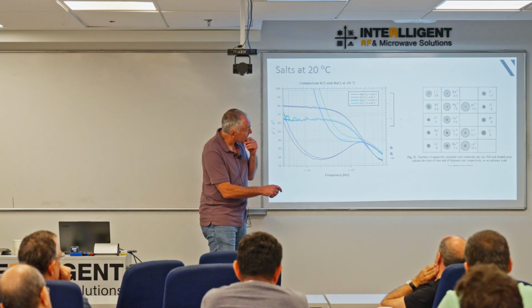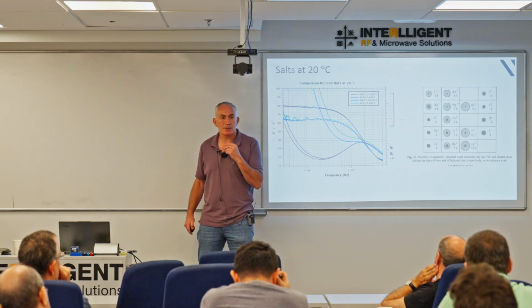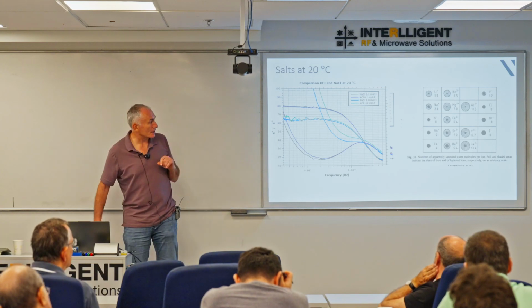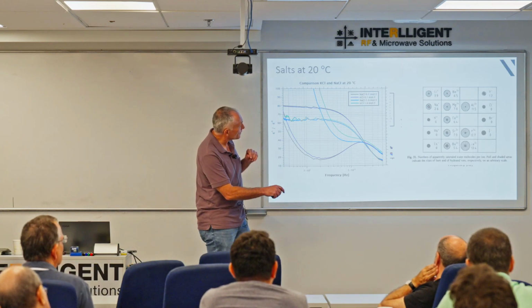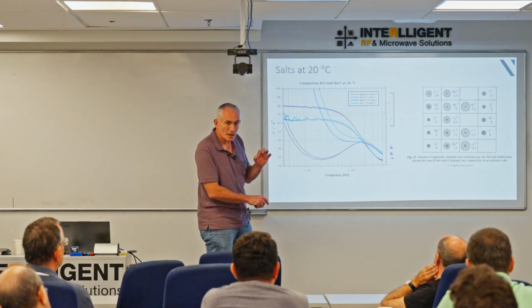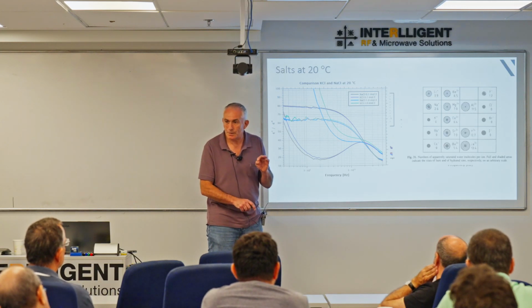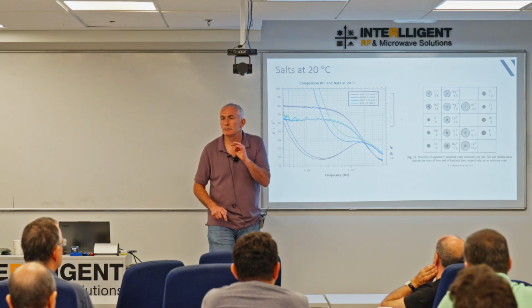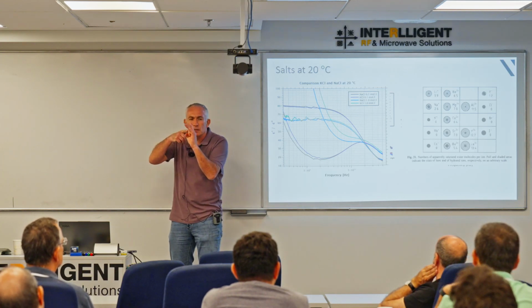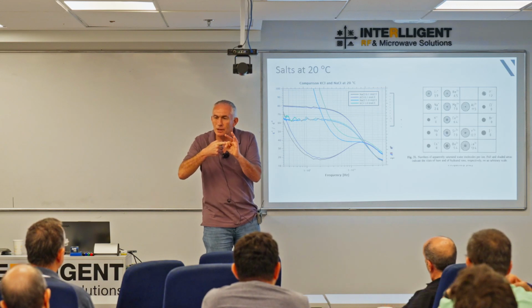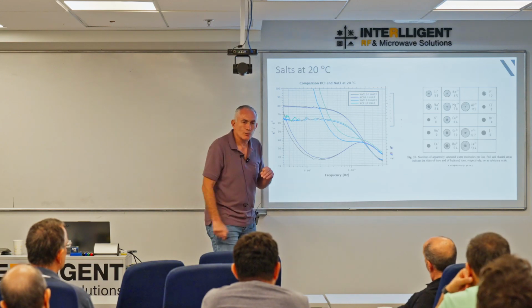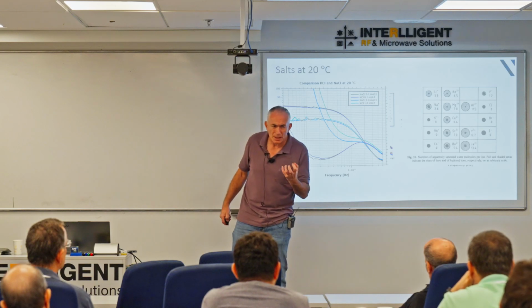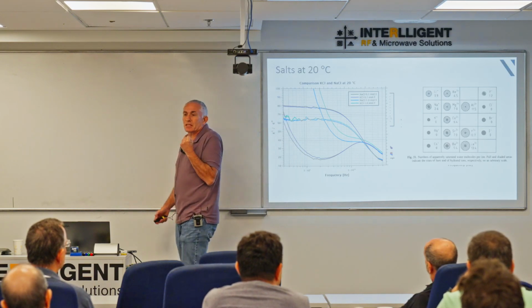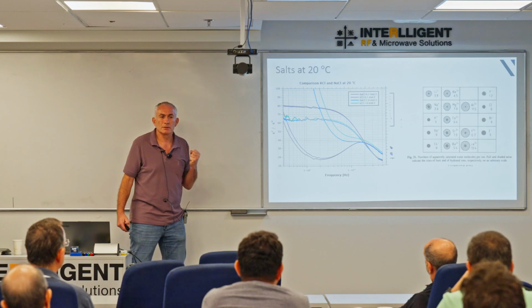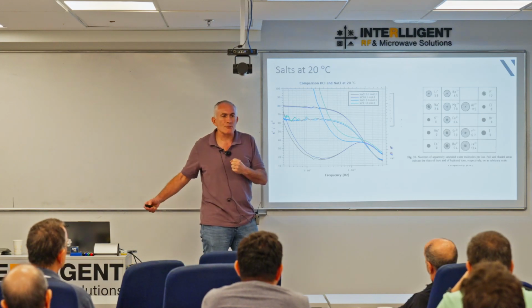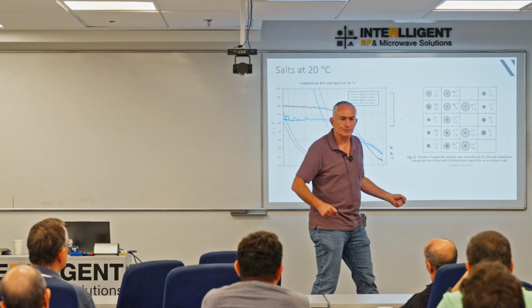Basically, you can see in terms of the sizes, they are very different. They are extremely different. Here's a sodium. That black dot is the size of the ion itself. It's at a certain size. It means there's a certain electric field close to its surface, which means it can hold a certain amount of water for a reasonably long time, about 20, 30 picoseconds in its immediate vicinity. Like it's grabbing. Yeah? Like a big guy running through a crowd and just grabbing people along with him.